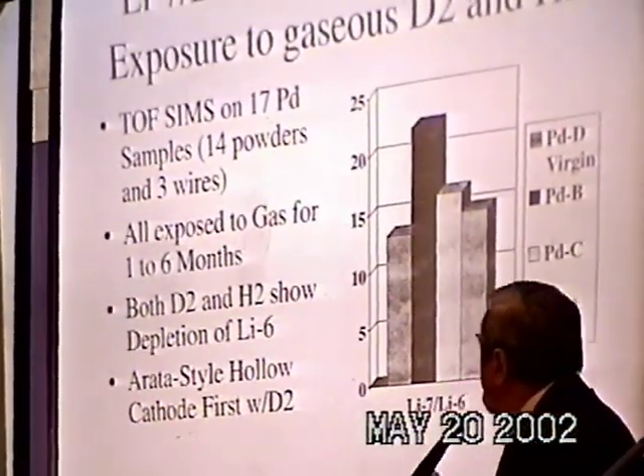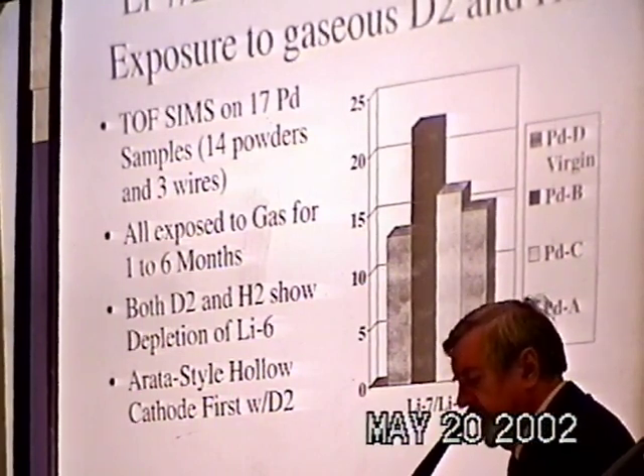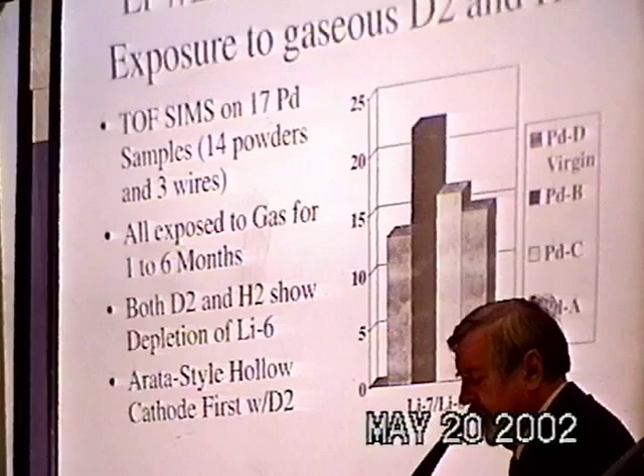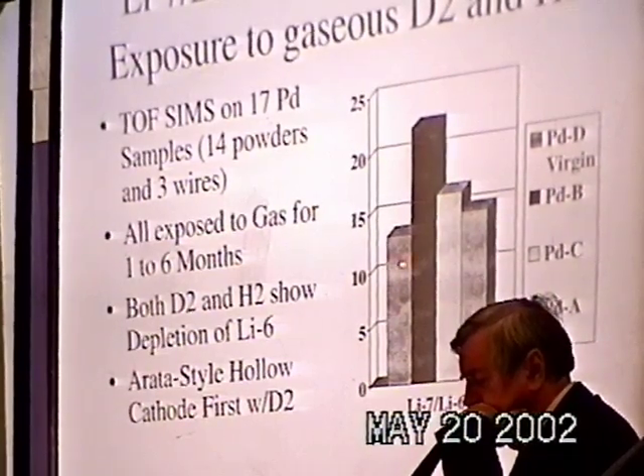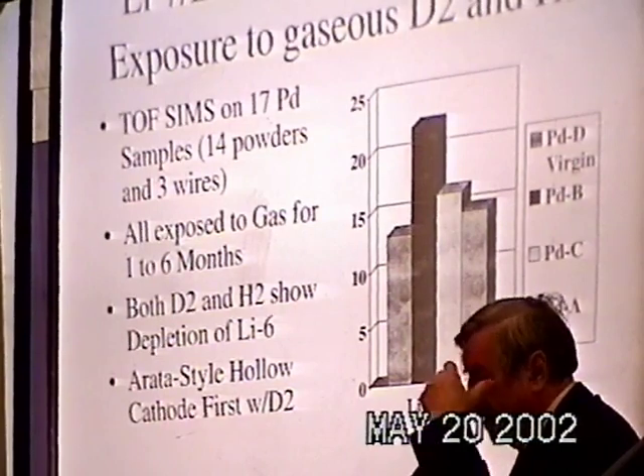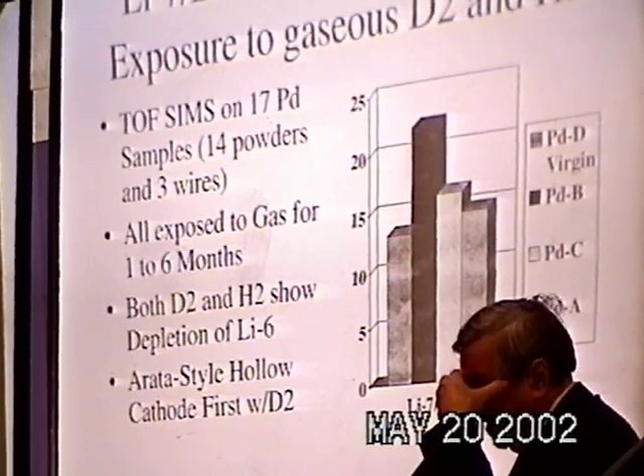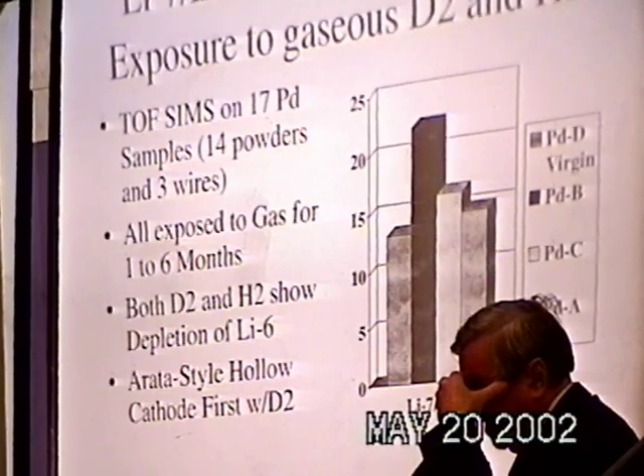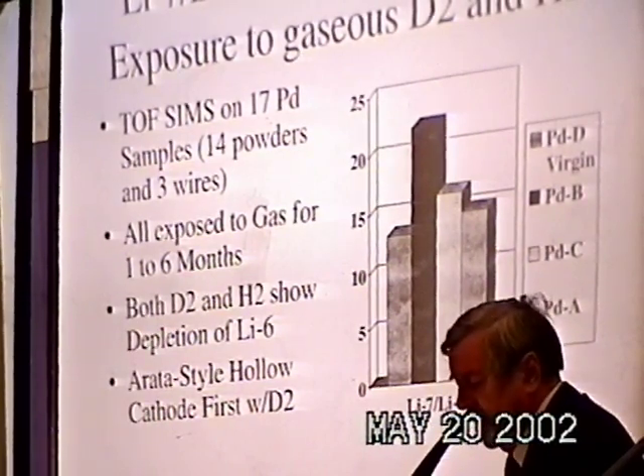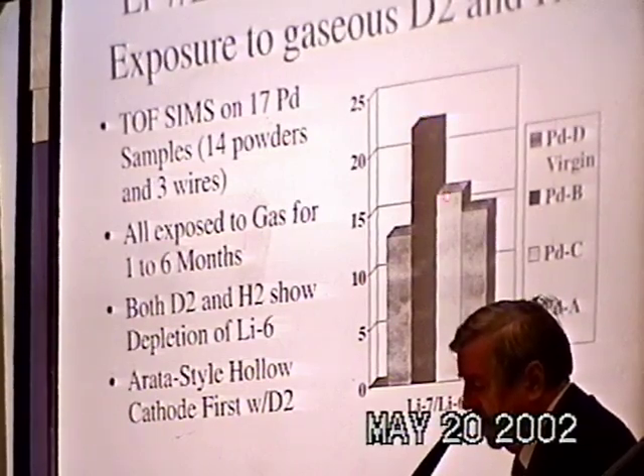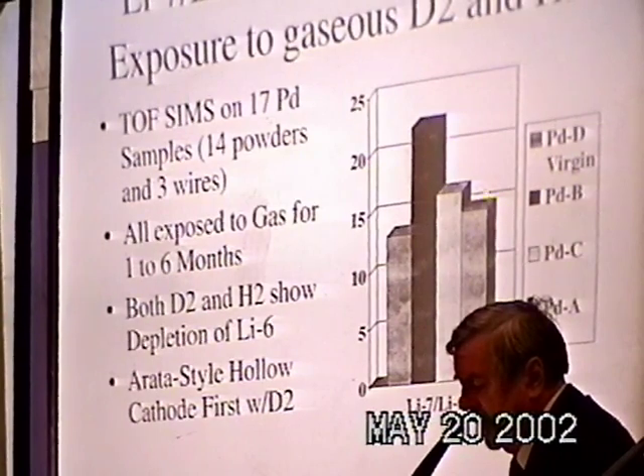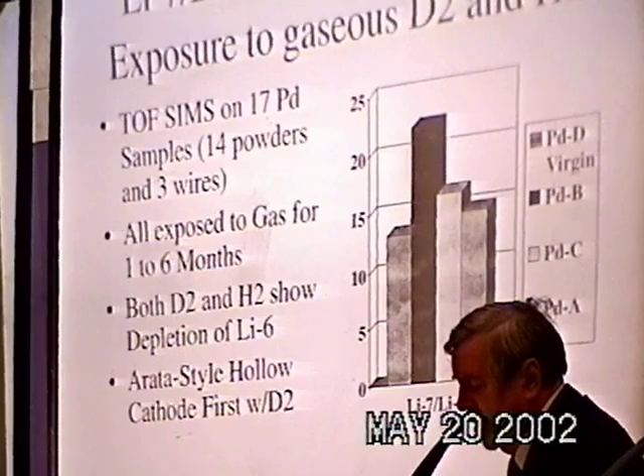And here's the first set of data that I took from 4 samples. The virgin sample on the left here has a ratio of lithium 7 to 6, which normally on the Earth is 12.48. You can see it's pretty close to normal. And these are the 3 active samples that produced excess heat in the Arata experiments. You can see that the 7 to 6 ratio ranges from about twice normal down to just maybe 10 or 20% above normal. But nonetheless, always above normal, implying a depletion in lithium 6 relative to lithium 7.